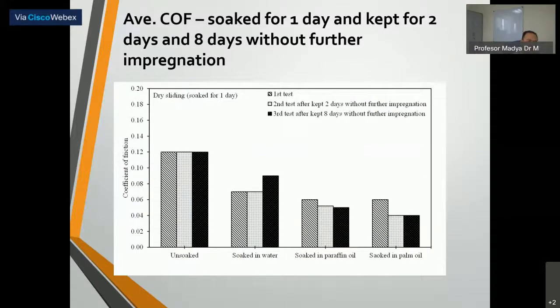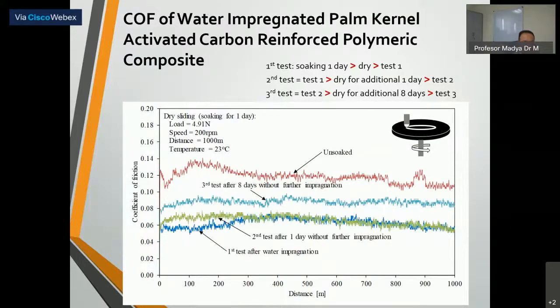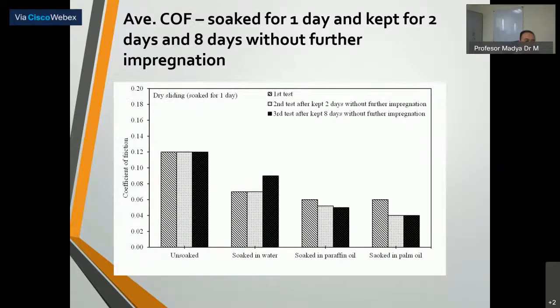Okay, this is actually the average, the summary of the coefficient of friction for these three graphs. We can see that for the unsoaked sample, the coefficient of friction is about 0.12. And when we soak in water and keep it without further impregnation, it is about 0.08. For paraffin oil, the trend is decrease, about 0.04, and also for the palm oil, 0.06. For the palm oil, we can see that the trend suddenly decreases, and we can achieve a coefficient of friction of about 0.04.